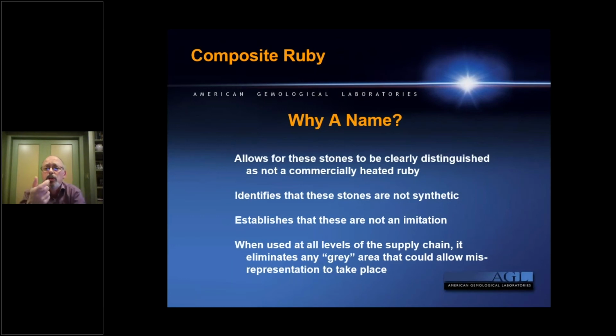There are two essential components to this material, hence a composite. You have natural corundum or ruby, and you have a high lead content glass. If you remove either one of these two components, you do not have this product. And so it really is a composite of these two materials. And in the same vein, it allows for these stones to be clearly distinguished from the more commercially heated rubies that we've talked about before. It identifies that these stones are not synthetic.